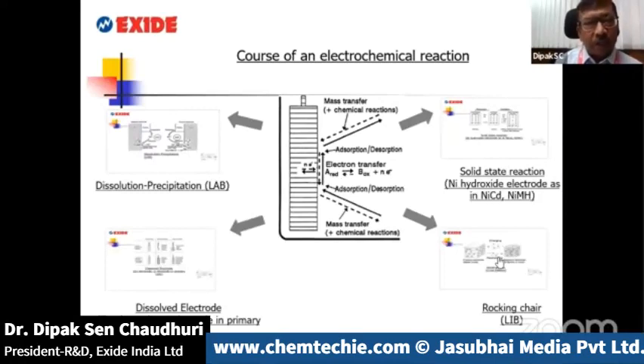In a lead-acid battery, the power is generated through an internal electrochemical reaction, which involves a dissolution, electrochemical reaction, and a precipitation. This requires time. And hence, a lead-acid battery, particularly when you are charging, doesn't charge as fast as a lithium, because in the lithium, there is no such steps like dissolution, reaction, then precipitation. It is just a mechanical translation of the ions through the space in between the electrodes, and therefore can be much, much faster. This gives lithium ion certain outstanding advantages, like it charges very fast.